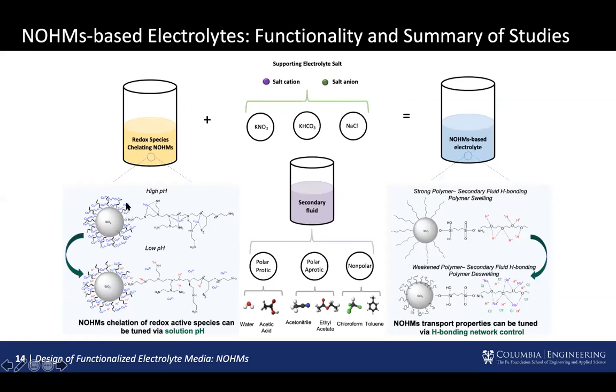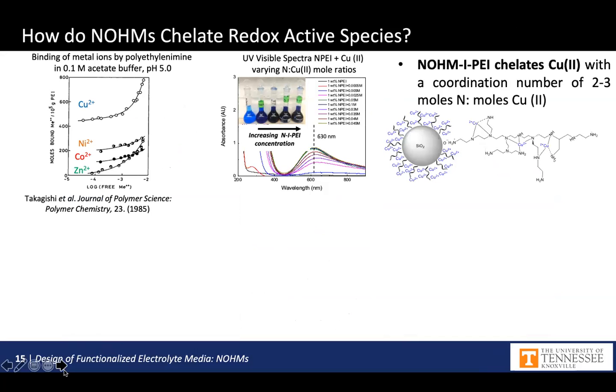So beginning here on the left, the chelation properties of NOHMs. Our first idea was whether we could have NOHMs that coordinate redox active species to improve their solubility. We approached the study first using NOHM-PEI, which has those amine groups, and we looked at the coordination of NOHM-PEI towards copper. We chose that because, as we can see here on the left, it has a higher binding energy towards copper than other metal-based species.